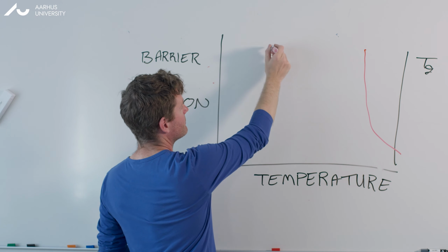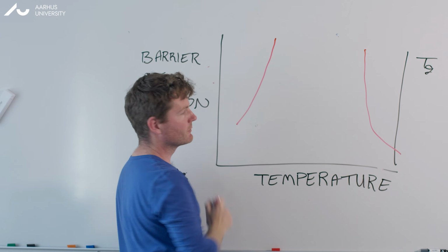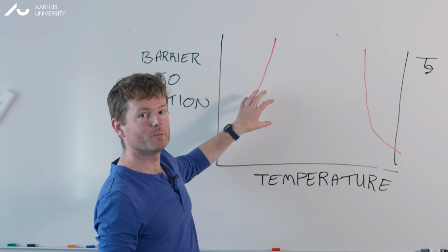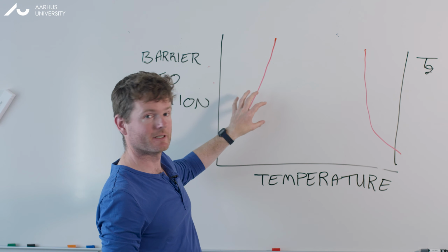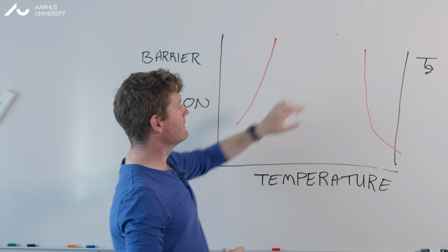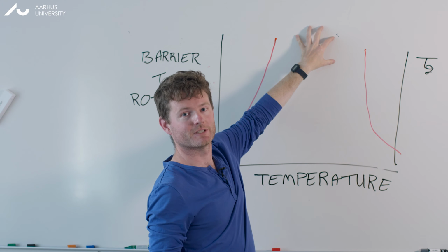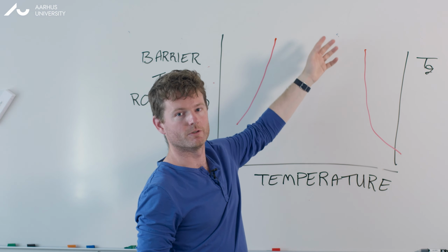But at very low temperatures, where the film is deeply supercooled, molecules also begin to rotate. This can only be attributed to the secondary relaxation process, and that's the key finding of this paper. In between, films are stable, and there's no rotation and no diffusion.